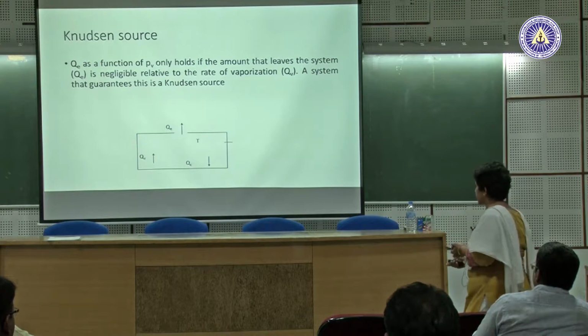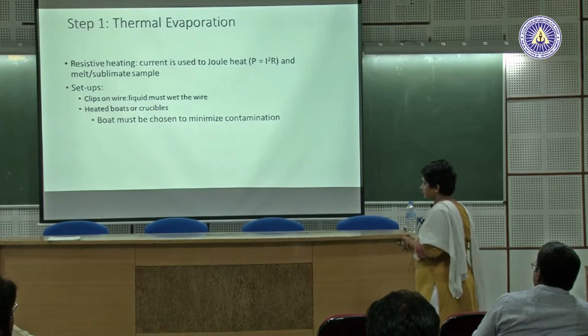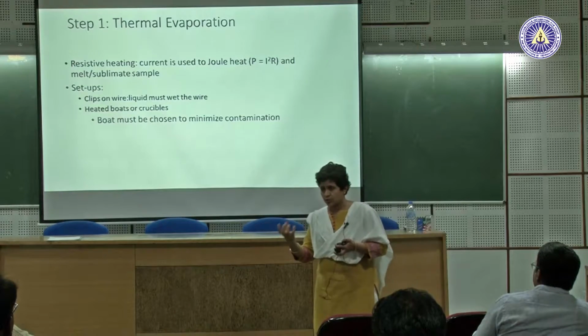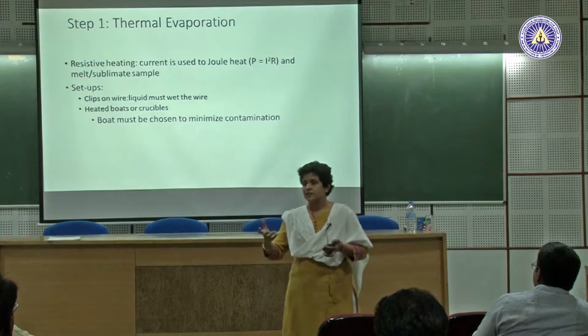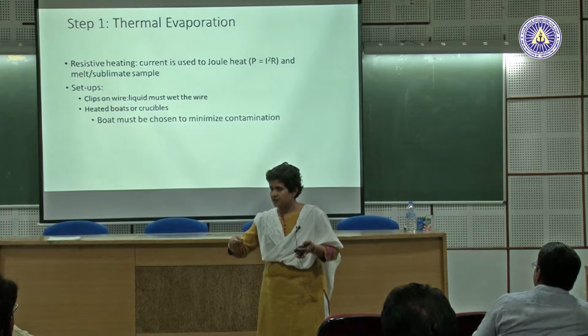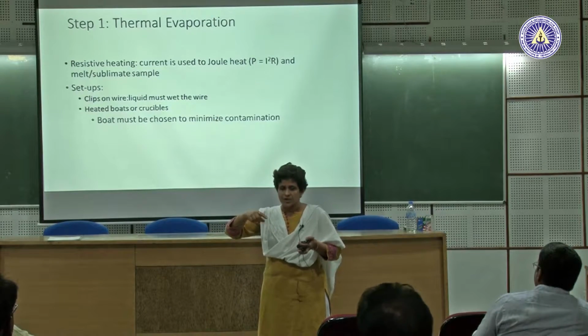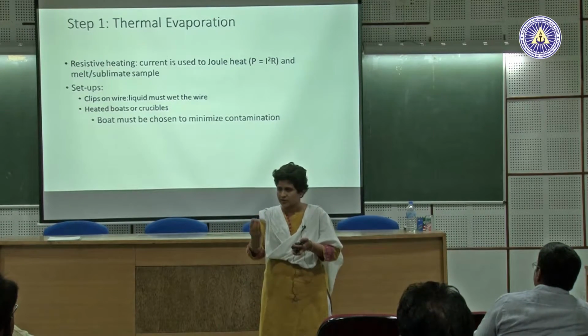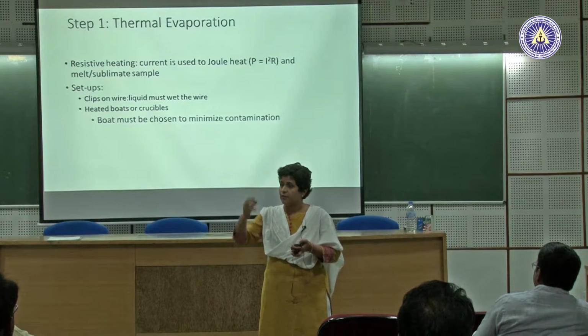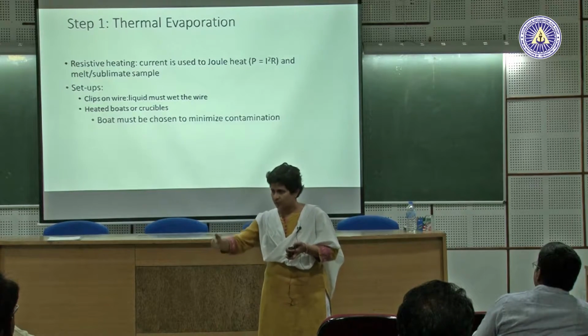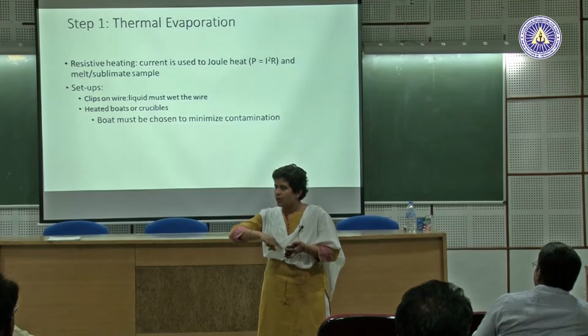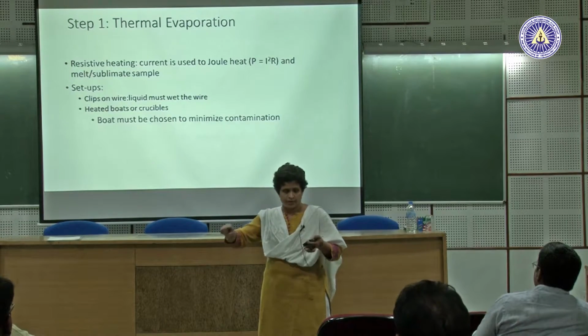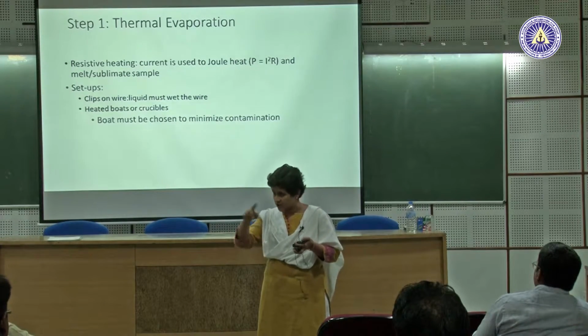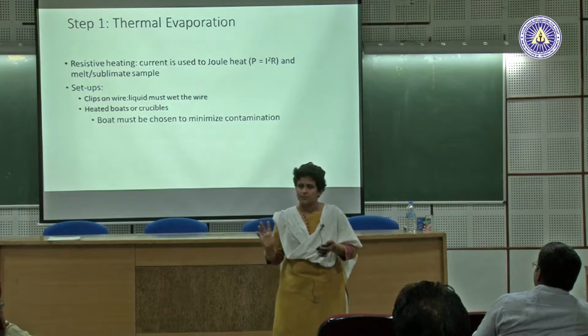And this is a very important point. If I just evaporate something and I don't control its temperature, if I heat it, let us say I put a heater and I am heating the material, my evaporation rate will have a curve. It will first initially start slowly, then it will go to a higher value. As the material gets reduced, it will again come down. So my flux as a function of time, while the film is getting deposited, is changing with time, which is okay for some applications.